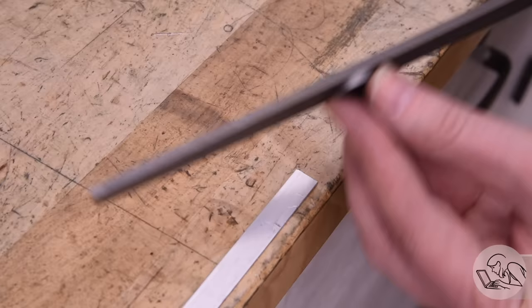It's got almost all of its toughness back. Let's do that file test again and you can see now when I put that file on there I can remove a little bit of material. The file is biting but just barely. So this is now softer than a standard file but just barely. I can feel it grabbing a little bit when I slide towards the cutting edges on the teeth as opposed to sliding backwards where it's glassy smooth.